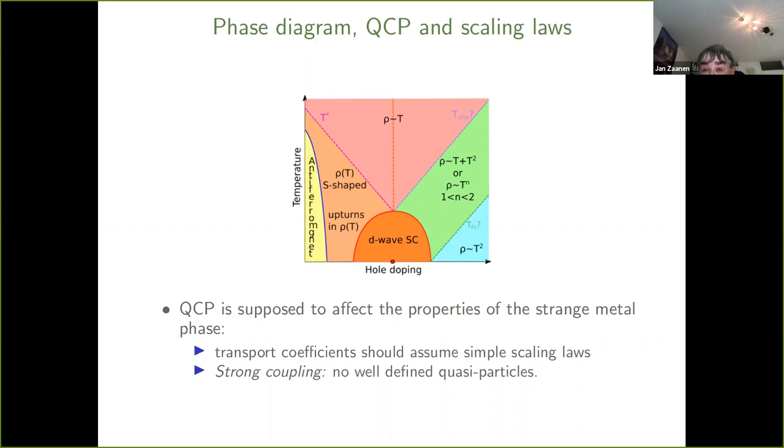There's old data by Loram and Tallon measuring the specific heat in the strange metal phase, above the superconducting dome. There's nothing to be discerned of an enhanced specific heat at the optimal doping. The evidence for these quantum critical phases is much more direct. It's really at the interface, it's photoemission, specific heat now, and also very new Hall effect measurements.